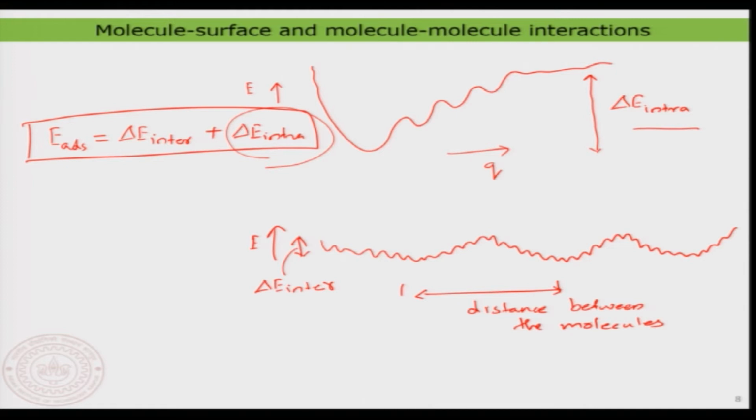There, some additional factors may also come into play: the molecules may start to orient in the third dimension as well, and not simply like on the surface, where we have seen that a planar molecule was just orienting with respect to the surface. But generally, when you start to make thicker layers, everything is controlled by the molecule-molecule interaction, and the molecule-surface interaction is kind of irrelevant. So, that is the summary.